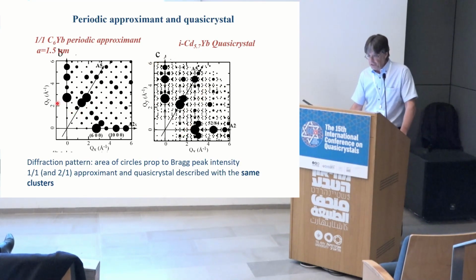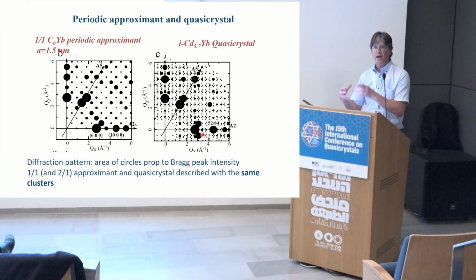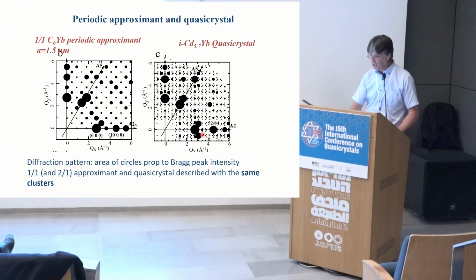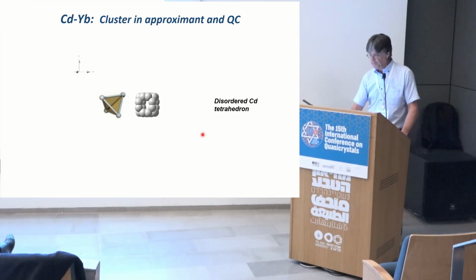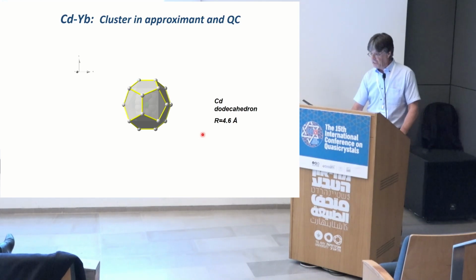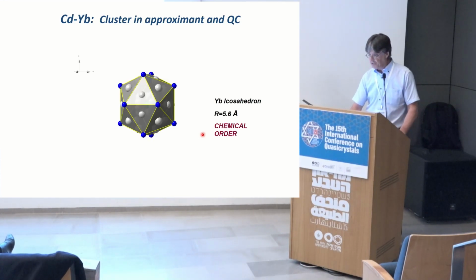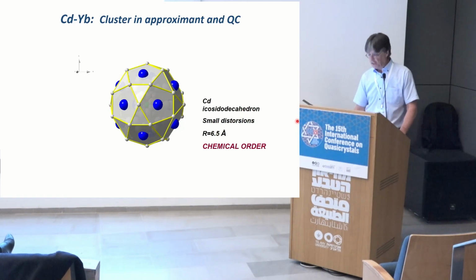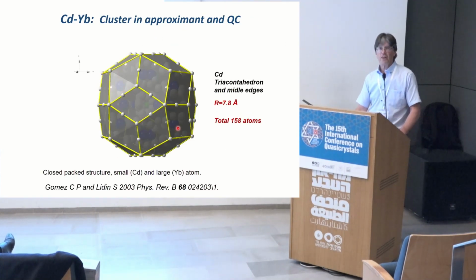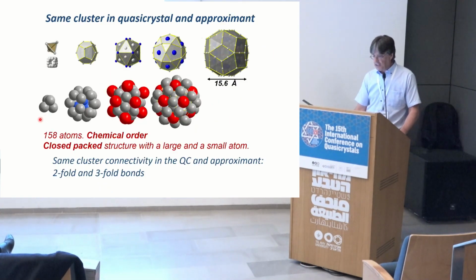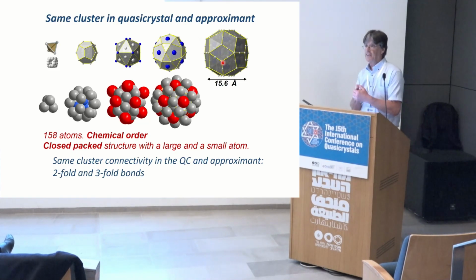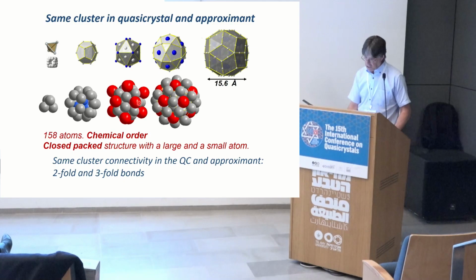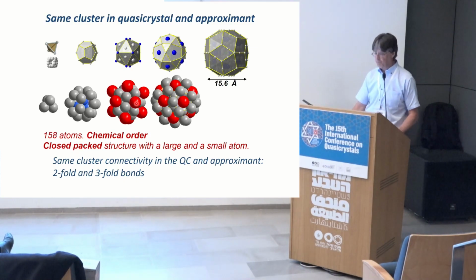But on the other hand, what you can immediately see is that the strong Bragg spots seem to be located almost at the same position. And that's a signature of the fact that both structures are built up with the same cluster. And that's what has been used to describe this structure. We start with a central tetrahedron, then we have cadmium in the shape of a dodecahedron, then an icosahedron, and this is only ytterbium atoms now. This is called an icosidodecahedron, and finally a large shell, which is called a triacontahedron. So it's summarized here. It should not be mixed up with fullerene or things like that. This is really completely different. We are piling up a large and a small atom, so it's a dense sphere packing, if you wish.